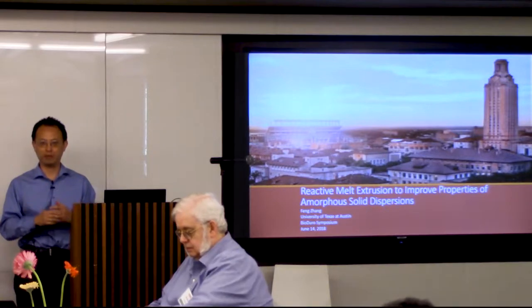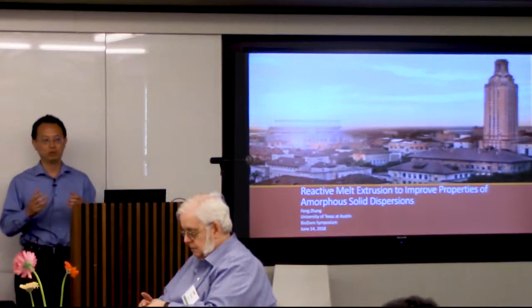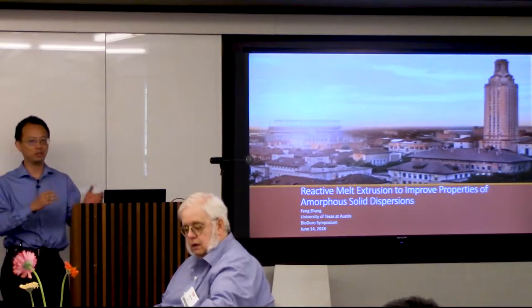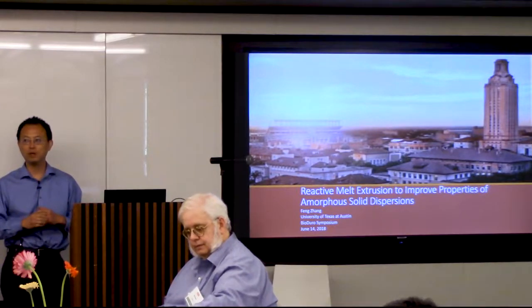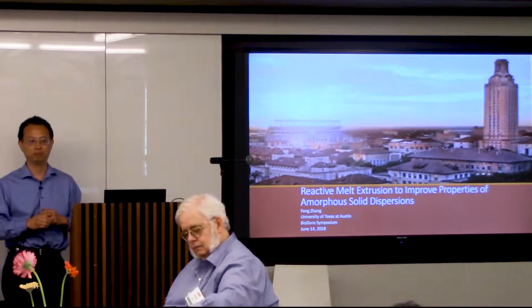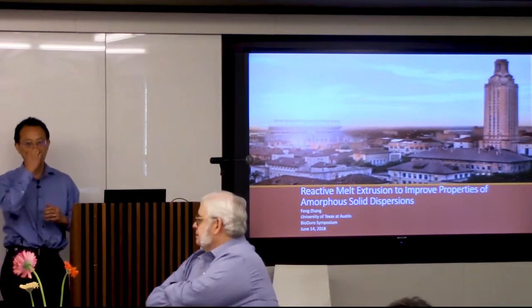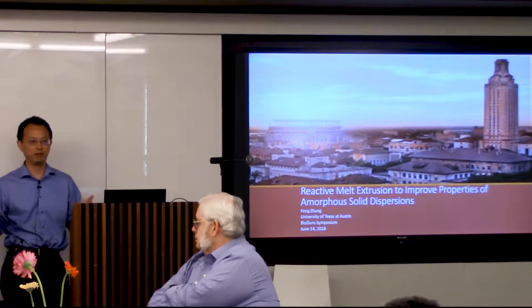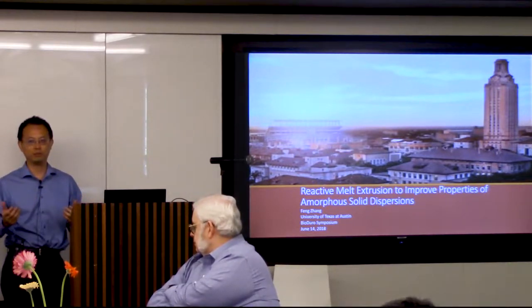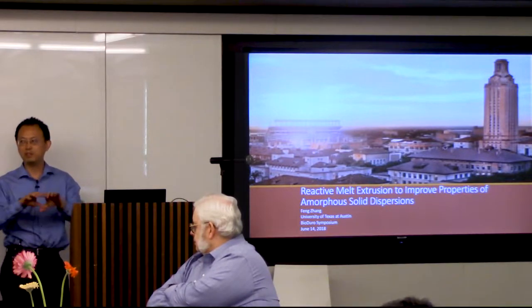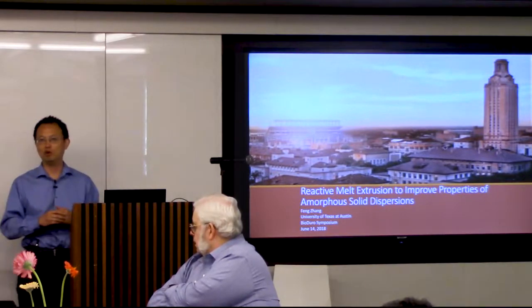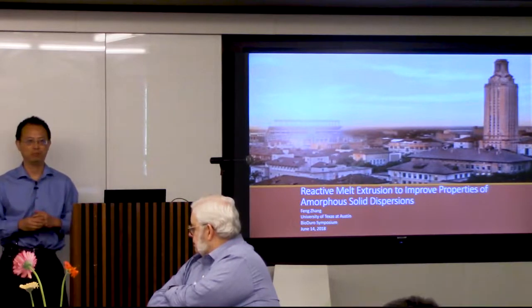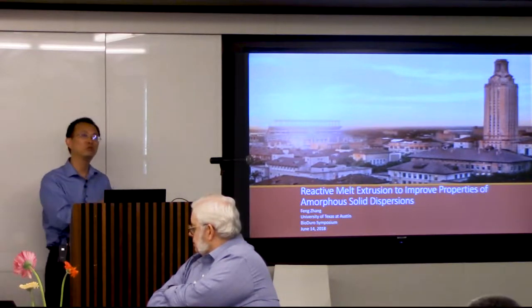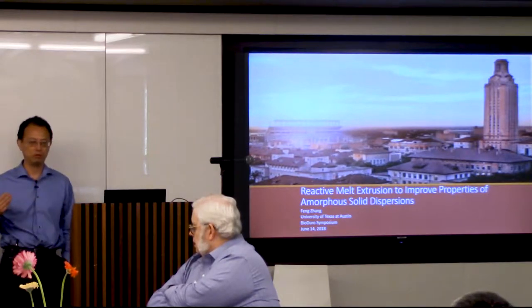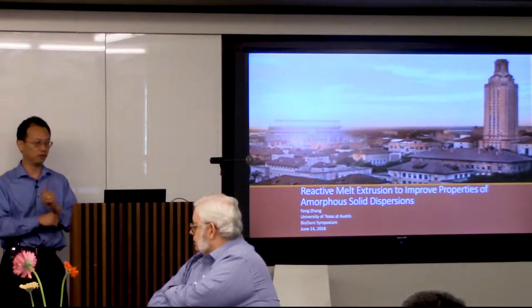The industry used to do batch process. So you're only exposed at 160 degrees C for 30 seconds to 2 minutes. And lots of drugs actually are stable for that. To give you a perspective, even in the commercial process, with a 27 millimeter extruder, they can run 30 kilograms, 40 kilograms per hour. But at any given time, inside that machine, you're only mixing no more than 300, 400 grams. So I think twin screw really changed pharmaceutical process.